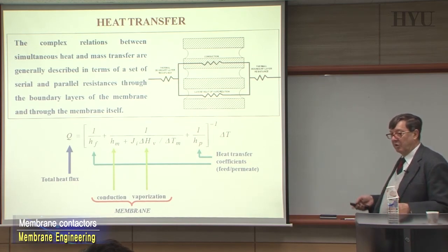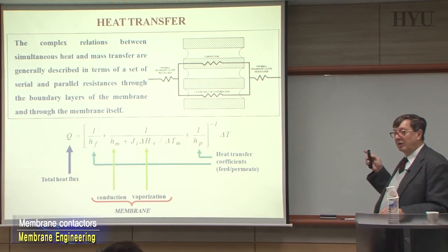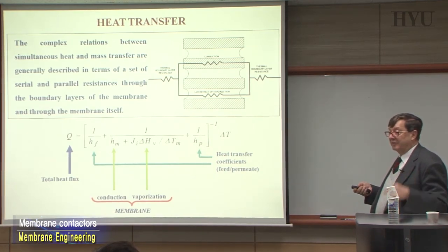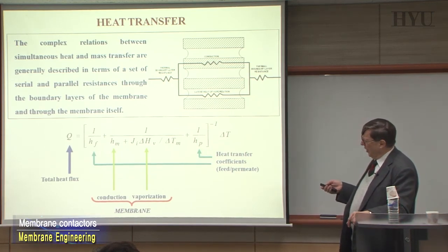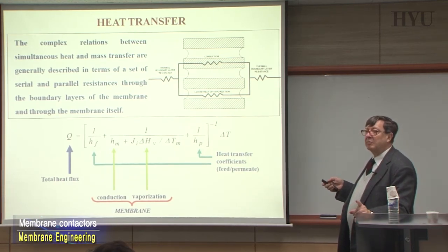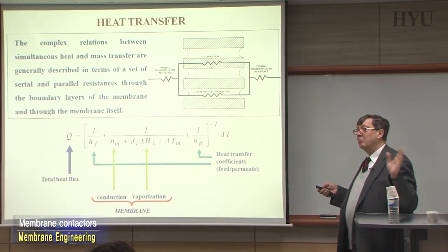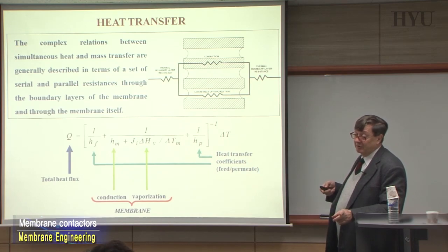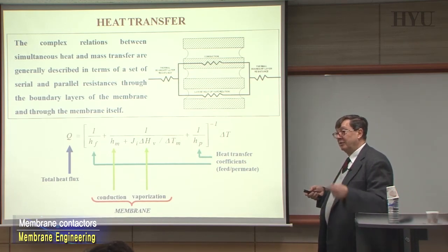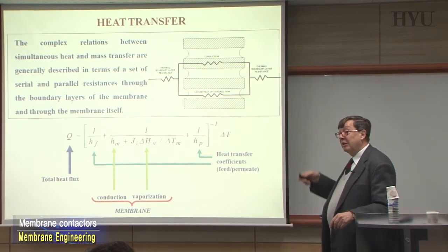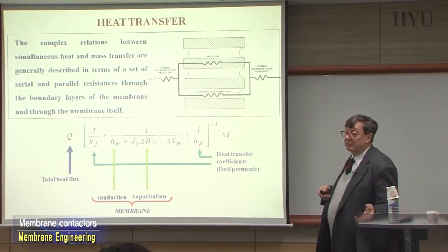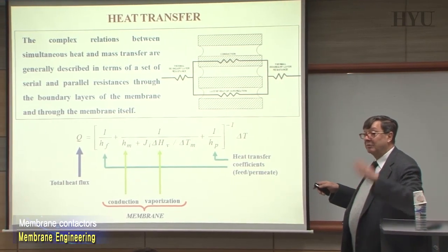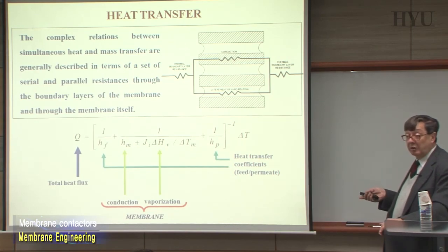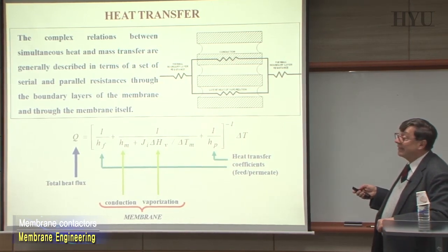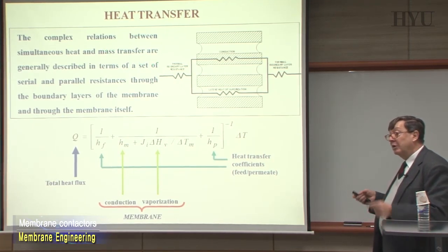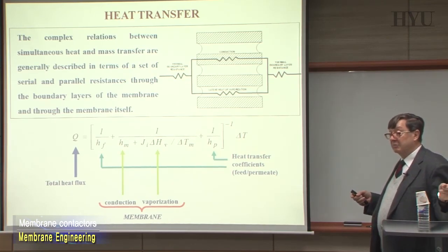However, keep in mind that there is a lot of space for improving the simulation modeling of the overall transport phenomena across our membrane distillation system, where you start to integrate, to combine together the heat transfer with the mass transfer. Because it's true that the mass transfer does not affect too much the driving force, but concentration polarization can affect not the overall mass transfer in principle, but the heat transfer. Because the heat transfer can be significantly affected by the changing of the mass transfer also. Until now, if you go to the literature, you'll find models describing one or the other phenomenon, not together. It's not easy, that is the reason. But we know that heat transfer can really kill your process. And that's why it's important to understand how heat transfer can be related eventually to the concentration polarization phenomenon.